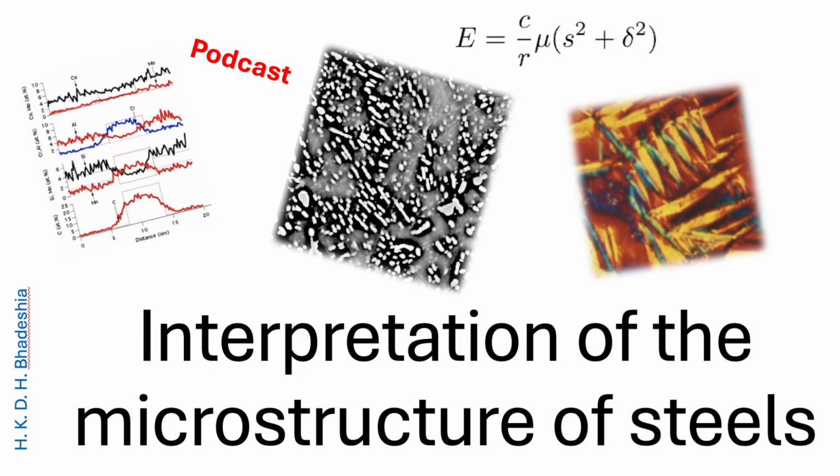Okay, now we shift gears entirely. We're stepping into the displacive transformations, where that mechanical strain is the core driver. We're talking thin plates. And martensite is the most famous product of this path. Martensite is the classic diffusionless transformation. It's initiated instantly when austenite cools below the martensite start temperature. The lattice change is described as an invariant plane strain. It involves both a huge shear, about 25%, and a slight dilatation. It sounds violent, atomically speaking.